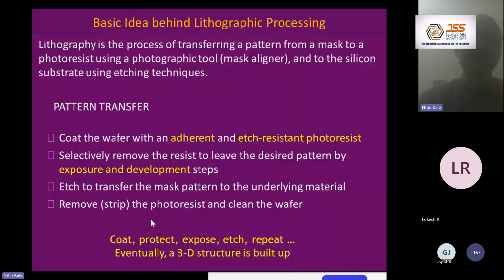Using lithography and using certain mask, you are going to activate or photo activate your resist at certain areas. And after activation, you can remove the photoresist from that area. And therefore, now your etchant has access to the underlying material which you want to remove. And after the material has been removed, you can strip away the photoresist. And therefore, you coat, you protect, you expose, you etch, and you repeat. So this is how you eventually build a 3D structure.